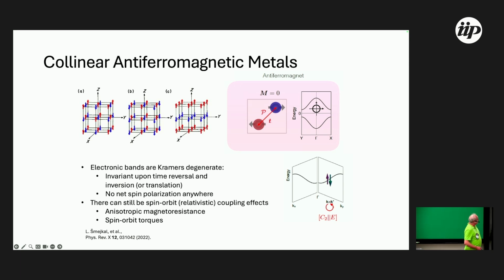Now, on the other hand, if you have an antiferromagnet, you have as much spin up and spin down, so naively you expect that there shouldn't be any spin polarization. And in fact, you can be more concise about it. Kramers figured out there shouldn't be a spin polarization. It doesn't really matter what type of antiferromagnet you're looking at, but as long as the atomic sites for the two sublattices are identical, there should be no spin polarization, like chromium, for example, maybe.